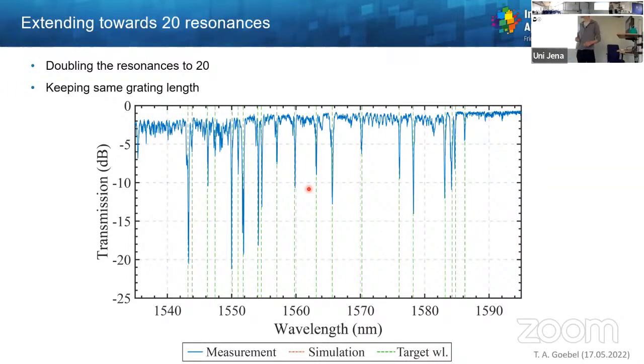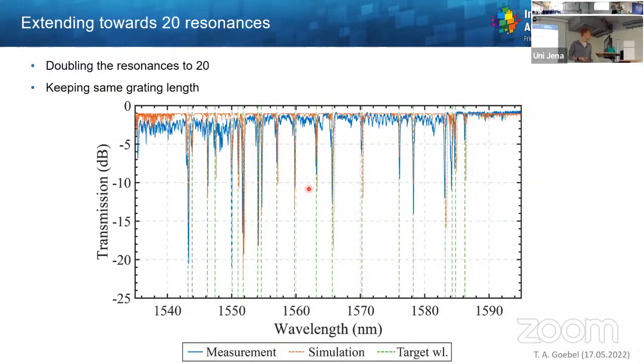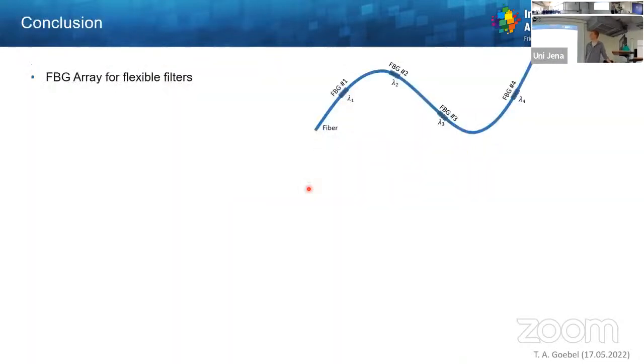However, now the suppression factor is not as high as before. So there might be some room for improvement by making it slightly longer and also maybe improving the stability of the system a bit. Also here, we can match the simulation and it predicts most of the resonances quite accurately. And so with this, I would like to conclude my talk.